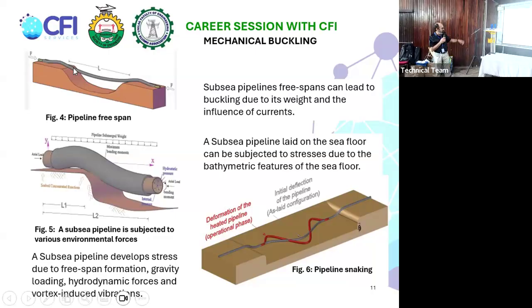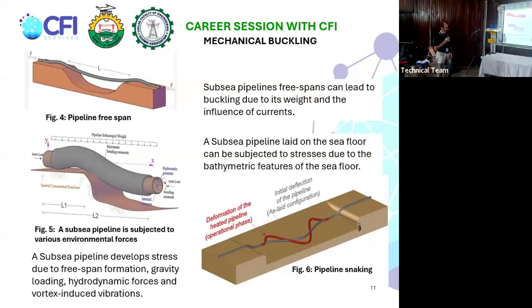Then you have the other one here. If pipe comes down a difference in height, also on that curve, it can buckle. Because another thing that can make a pipeline buckle is temperature inside the pipeline. Stress, thermal stress in the pipeline over long distances. It can make the pipeline shrink or lengthen or expand. And that could also be a reason for buckling.